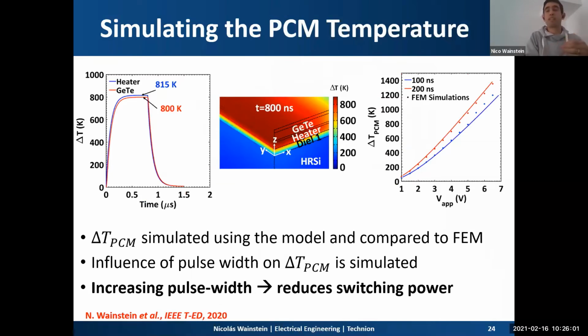The electrical thermometry setup that we built doesn't provide us accurate information about the PCM temperature variation. Therefore, we model the IPCS also in COMSOL Multiphysics as a finite element model, where we can see in the right figure that the compact model, that is the solid line, and the finite element method simulations, that are the dots, agree. It can be appreciated also that increasing the pulse width between 100 nanoseconds and 200 nanoseconds reduces the reset power. There's more time to achieve the steady state temperature.